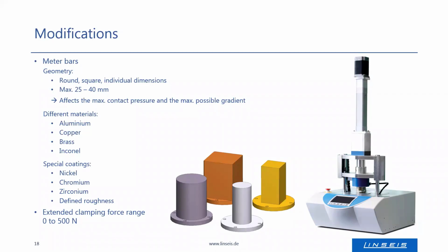A further modification which is possible is extended clamping force range from 0 to 500 Newton, and this setup is shown here on the right. So here there's an extended clamping force range, and one can see clearly that the top gets longer due to this modification.